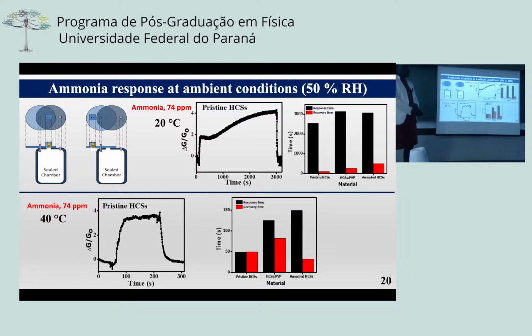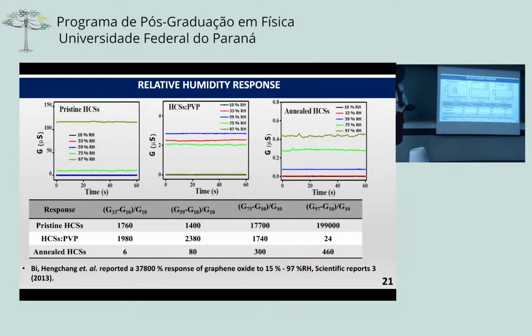However, while doing this measurement, we noticed that whenever humidity changed, the measurements changed. So the data was really not very reliable. Therefore, we decided to look into the relative humidity response instead of ammonia. We created humidity levels between 10% and 97%, and we then measured the response of these devices at the various relative humidity.